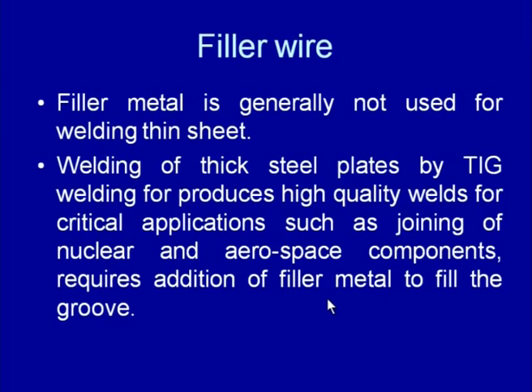Under those conditions, when thick plates are to be welded, the filler material is added in the form of rods of different sizes. The rod is placed in the arc region so that it melts and helps to supply the metal between the plates to be joined. In this case, the spattering is found to be minimum, or most of the metal from the filler rods we can deposit without loss. So, the deposition efficiency is found to be much higher with the GTAW process.